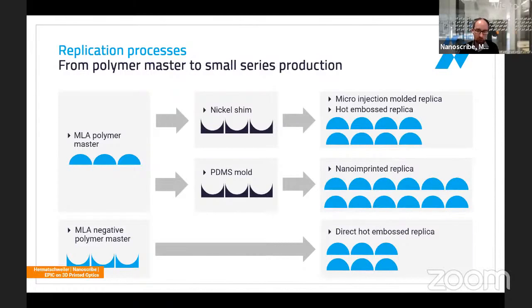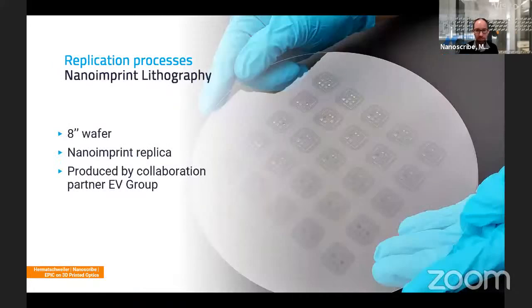And our process is also fully compatible with standard mass manufacturing processes. So if you think about mass fabrication of structures, you can either create a nickel shim, or you take a soft mold based from a polymer master, and then you do either injection molding or hot embossing, or you do nano imprint lithography. And as one exemplified structure, you see here an 8-inch wafer. This has been done in collaboration with EVG as collaboration partner. This is based on nano imprint replication.